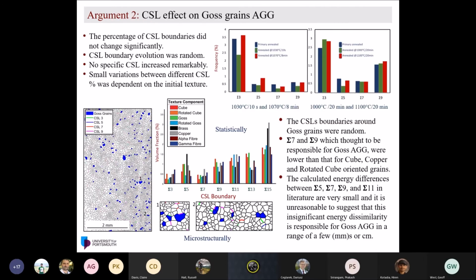Next, we tried to validate the second argument, where we try to understand the effect of the CSL boundary on the growth rates. We looked at all the sigma 7 and sigma 9, the two main sigmas, or CSL boundaries, believed to be responsible for abnormal grain growth. When you look at the frequency and the volume fraction, in fact, the percentage didn't change significantly after we annealed, and their distribution was rather random.